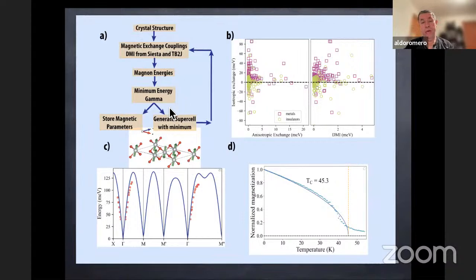Here, we created a method that, by taking the crystal structure that we found, is able to detect the most important magnetic parameters. In the B side of this plot, you will see some of them, how they look. But what matters to me is that you notice the two plots on the bottom. The left-hand side corresponds to the so-called magnon spectra. The dots correspond to the experimentally measured magnon spectra, and the line corresponds to the theoretical one. This corresponds to nickel oxide, a very well-known antiferromagnet. You can see that we recover not only the magnon spectra, but we can also see where the magnetic moments are pointing and what the most important interactions are.